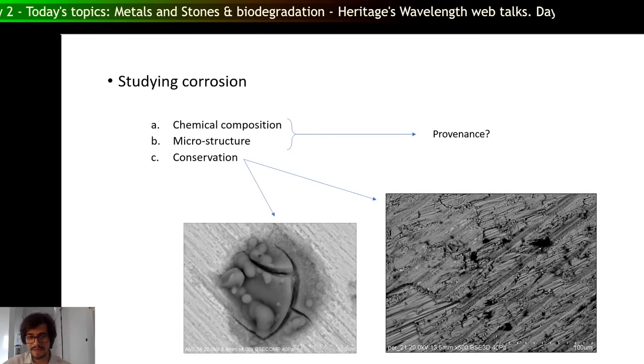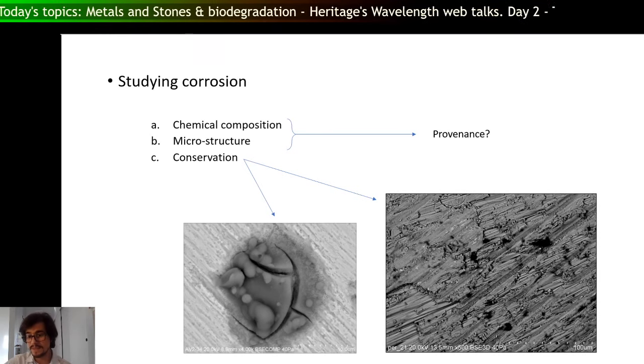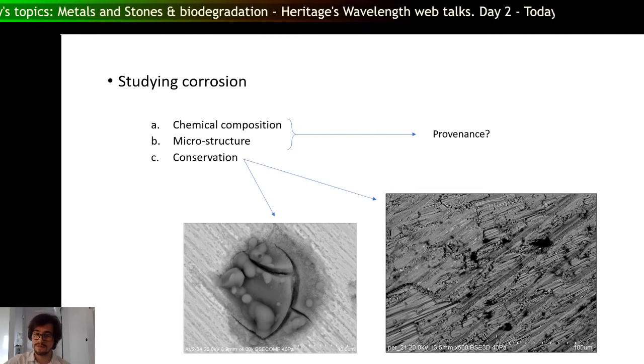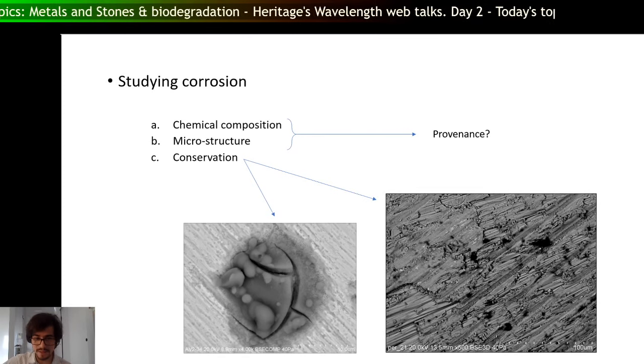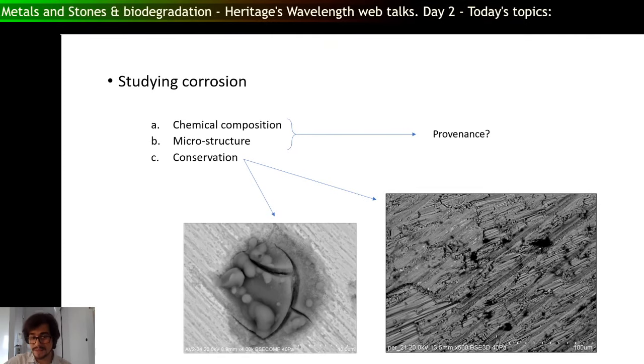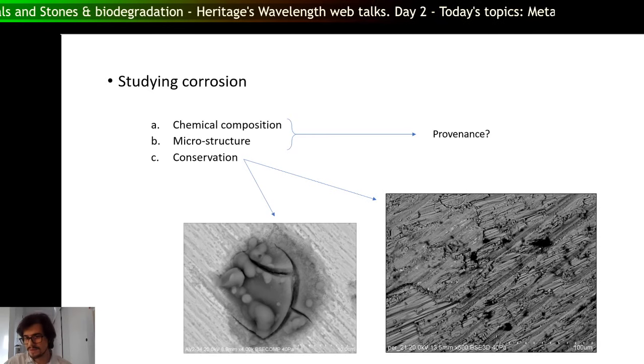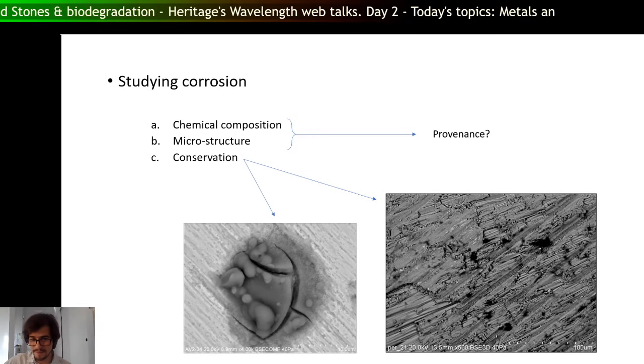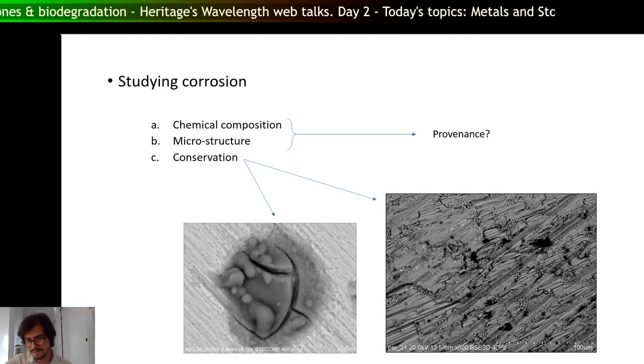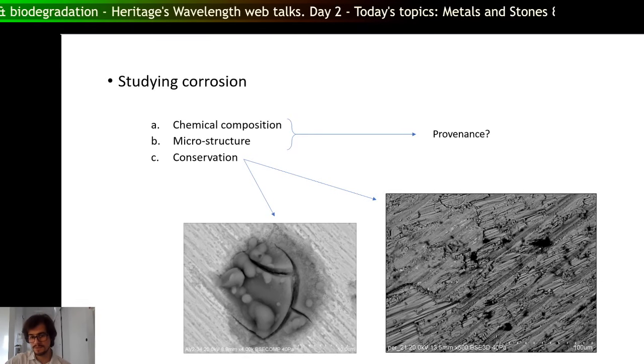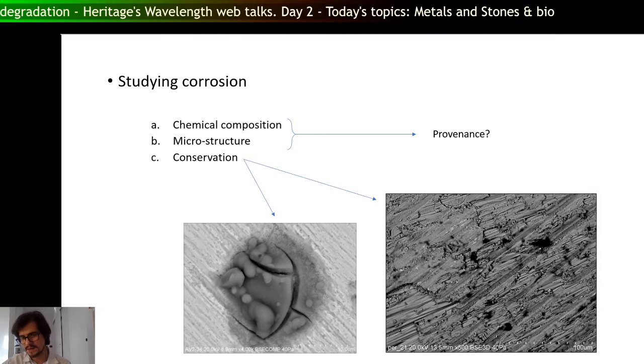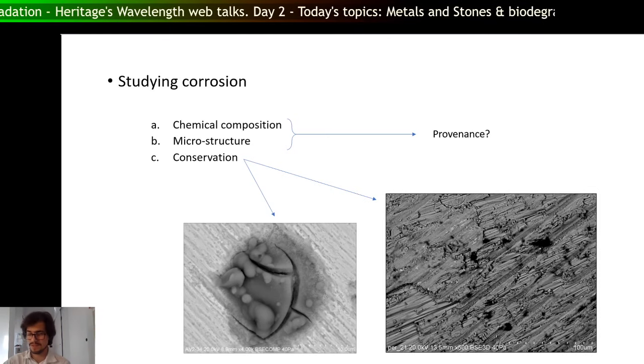There are ways to stop that and to treat bronze disease, but this is the most aggressive corrosion that you can find in bronzes. As you can see, the detail in this picture on the left is literally an open crack on the material surface. This is one very small pitting corrosion. This image was taken with an SEM, scanning electron microscope, and I'll get into more detail further on.